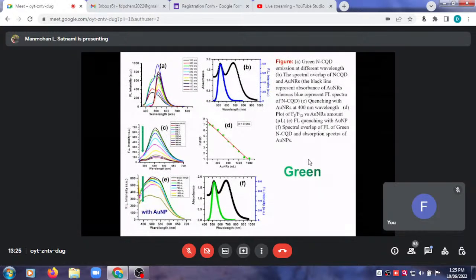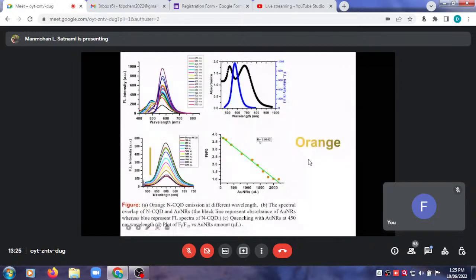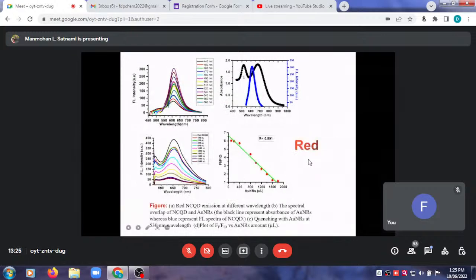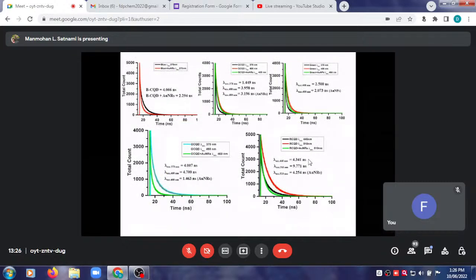Then orange. तो orange का जो कार्बन क्वांटम डॉट हमने बनाया, that gives emission which is partially overlapped with the 520 nanometer band and partially overlapped with the 650 around band of gold nanorod. And see the red one. So red emissive carbon quantum dot, the fluorescence of red emissive carbon quantum dot is not overlapping anymore with the 520 nanometer band of gold nanorod, but somehow some amount of overlapping is there between fluorescence emission of carbon quantum dot and gold nanorod. So on the basis of this, we developed a sensor for determination of glucose and cholesterol.